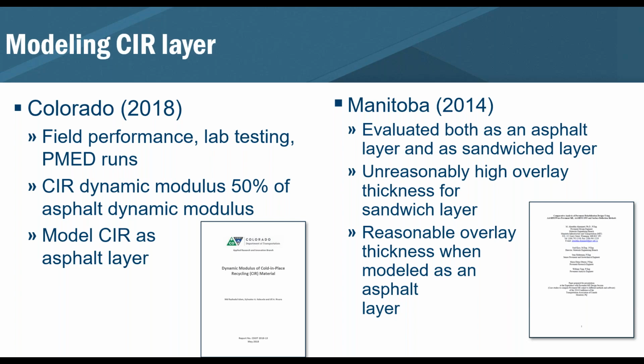They actually looked at it both as a stiff layer, as an asphalt layer, excuse me, and as a sandwich layer. But they found that when running the PMED results, it showed that the sandwich layer had unrealistically or unreasonably high overlay thicknesses, where when they ran it as an asphalt layer, it actually came to be a little bit more reasonable as far as the overlay thickness.